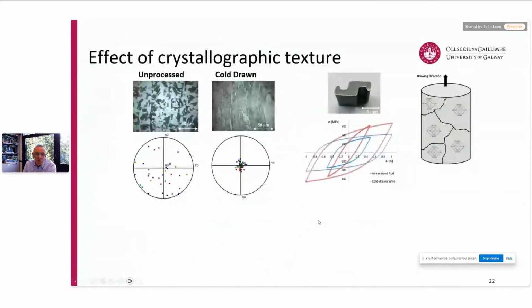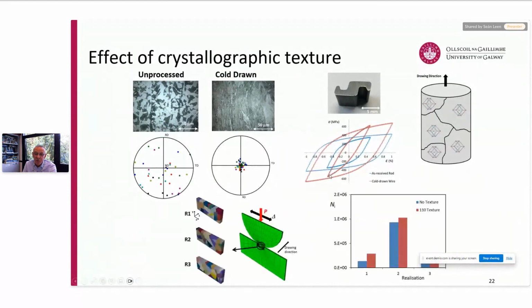And then we've also looked at the effect of crystallographic texture between the unprocessed steel, which we've tested, and the cold-drawn steel, which we've also tested. And you can see significant differences in terms of cyclic plasticity for those 2 cases. We've characterized that in terms of our models, and you can see that we're applying that to these micromechanical contact fretting models. And you can see that in general, we're seeing a beneficial effect of the texture, but probably not a dramatically beneficial effect. I think that's my last slide, apart from my conclusions.